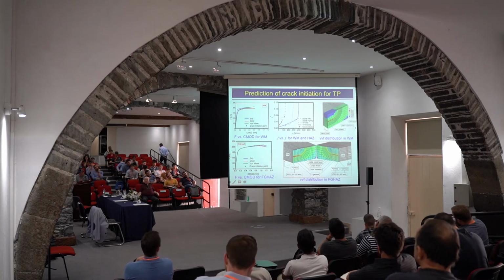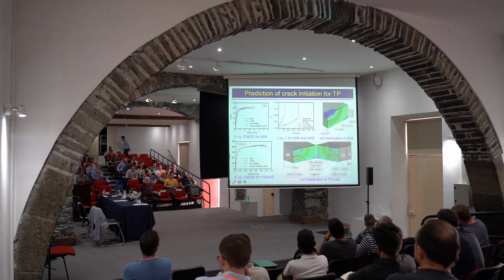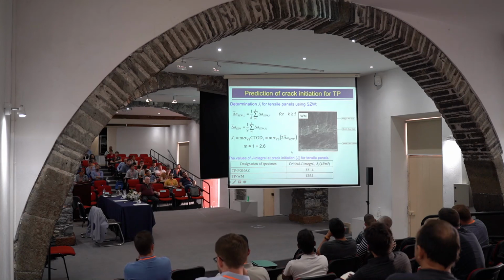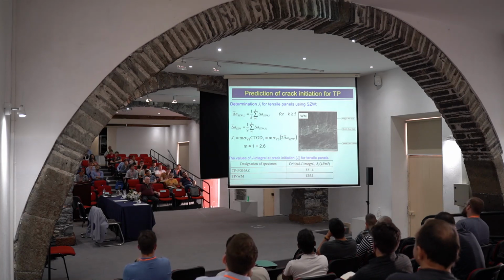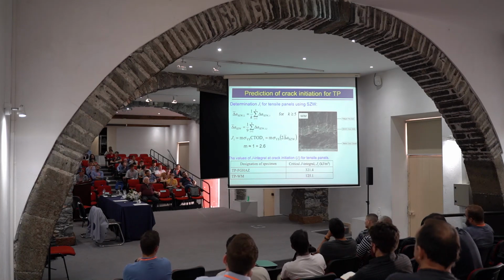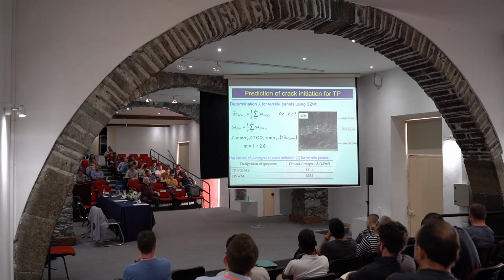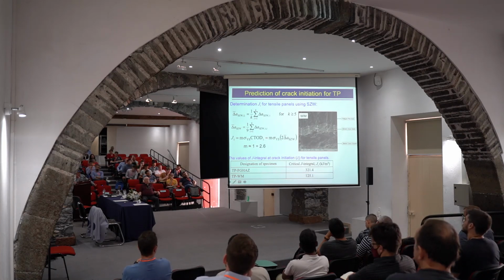You can see also distribution of volume void fraction, which is very similar to strain distribution. This is how we evaluated J initiation for tensile panels. Since it is not testing according to standard, we used stretch zone width to get 321 for heat affected zone and 120.1 for weld metal.